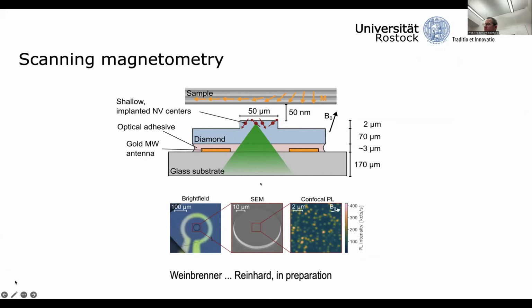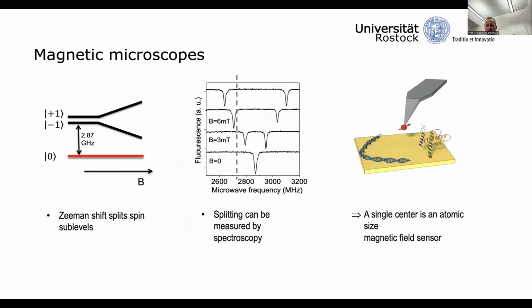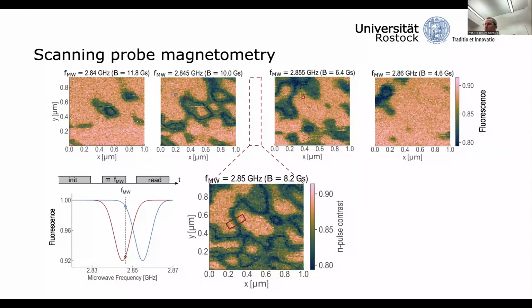It turns out it's still advantageous to isolate a roughly 100 micron-sized platform on top of them. This looks a little bit like a tip, but it is a very blunt tip, and it is much easier to fabricate than the AFM tips made from diamond. Also, this blunt tip contains more than one NV center. So with the same sensor, we can have a choice of the number of NV centers that we use. And this is something that will be useful very soon.